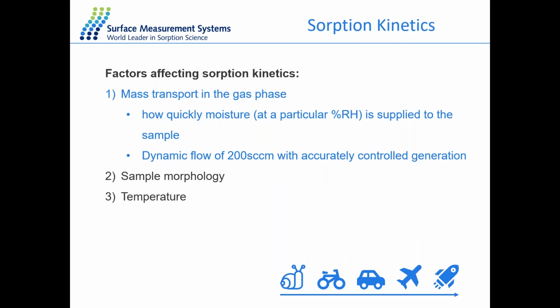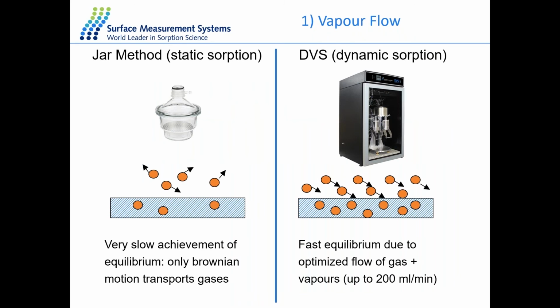So for the first factor, the mass transport in the gas phase is about how quickly the moisture is supplied to the sample. And in the DVS system, this is optimized by having a dynamic flow of 200 SCCM of vapor to the sample to ensure a very quick delivery of moisture to the surface of the material. And this is one of the advantages of the dynamic system, that in the DVS, we have a continuous flow of the probe molecules to the sample that makes a fast equilibrium at each stage.